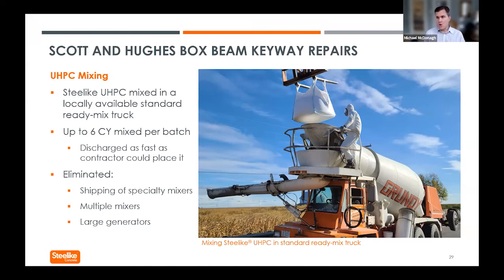Steelike is the only commercial UHPC supplier that can and does do this on a regular basis and successfully. For this project, up to 6 cubic yards were mixed per batch, although we do have the capability to go up to 7 cubic yards per batch. With these very large volumes, essentially the contractor can discharge it as fast as they're able to place it.